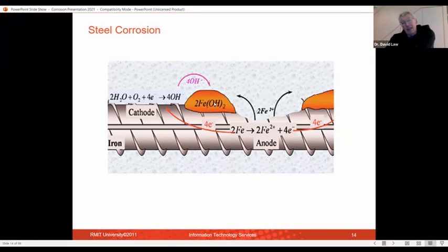This occupies a larger volume than the steel, because the steel is now combined with our oxygens or our hydroxyls, and so it puts a stress on the inside of the concrete, and so the concrete will collapse. And you will get cracks, you will get spalls, and you will get failure of your concrete. And that is how our steel corrosion is initiated when we have our chlorides.